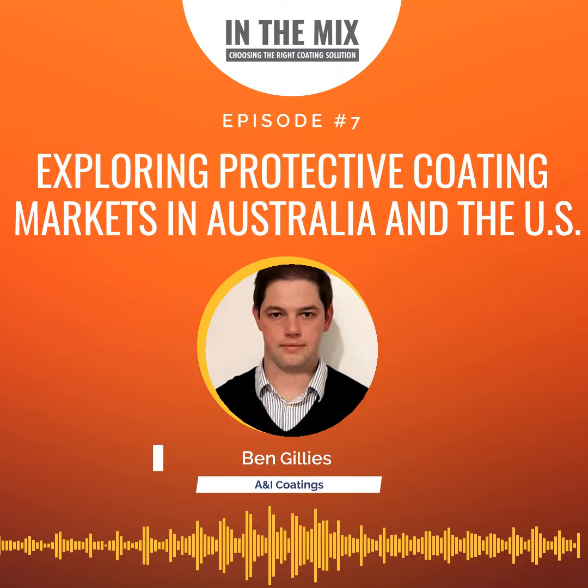And then in terms of actually selecting the coating system, we're a firm believer in using fluoropolymer for probably 90% of applications, because if it's in a coastal region, then it's proven itself time and time again to be more corrosion resistant because it reduces the ingress of corrosion initiators. But when I say that, in Cairns, for example, we might have a coating system that's 350 microns total. So it might be 75 microns of zinc rich epoxy, 200 microns of micaceous iron oxide epoxy, and then the fluoropolymer top coat. And that's a pretty bulletproof system.